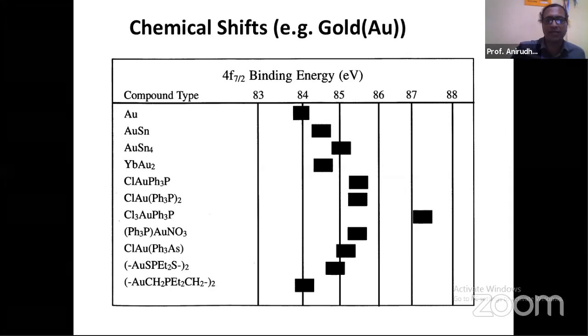Now coming back to the problem which I raised just now, it is not showing the 1s binding energy for gold. It is showing the 4f binding energy for gold. The reason is that gold is not a light element. It is not a small atom. It is a large atom. When you are using soft X-rays like aluminum K alpha and magnesium K alpha, the energy of those X-rays is not penetrant enough to knock off a 1s electron from its core. It cannot penetrate so deep. So it is limited to some level, which for gold is 4f. In fact, we will experience the same thing for iron, because these X-rays cannot penetrate beyond the 2p levels for iron.